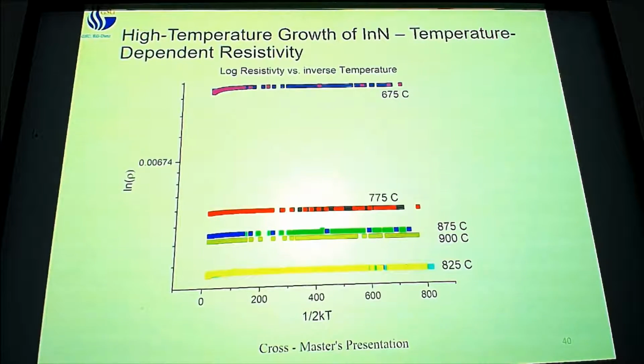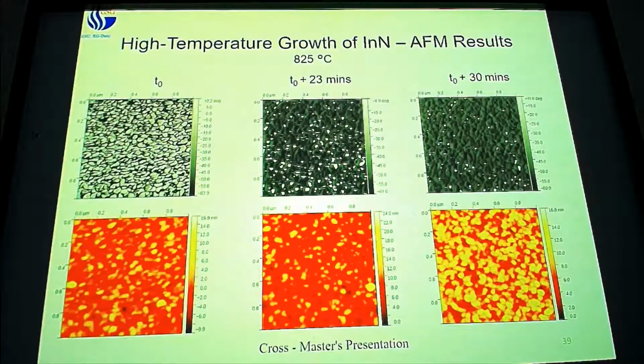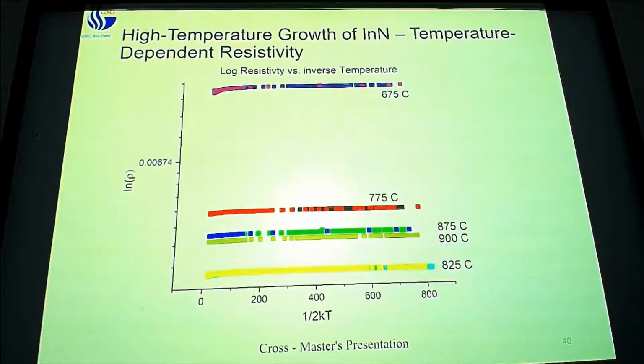But the other thing that we need to pay attention to here is that this change is extremely small. So we're sitting at 0.00674. This is a log scale. And the program I used wouldn't even give me another set point on there unless I shrunk the data down so that I could actually see another point on the side here. So these measurements are actually very close together. So it is possible that any variation I see here is artifact. But there is a trend, and it is broken by that sample, which was demonstrated in AFM as well. So moving forward, talking about proposed work and my conclusions.